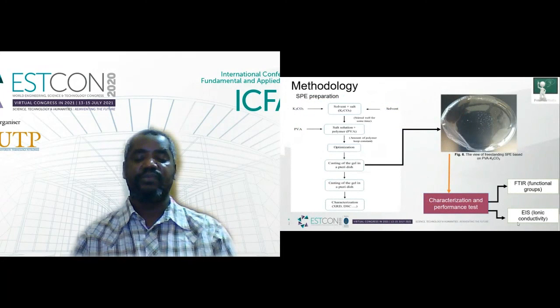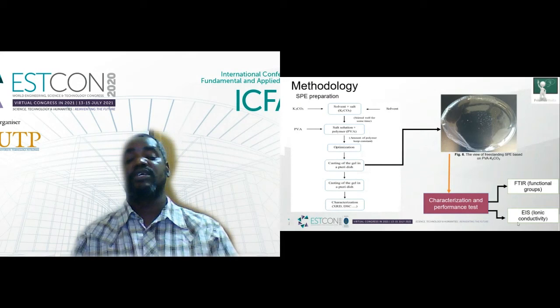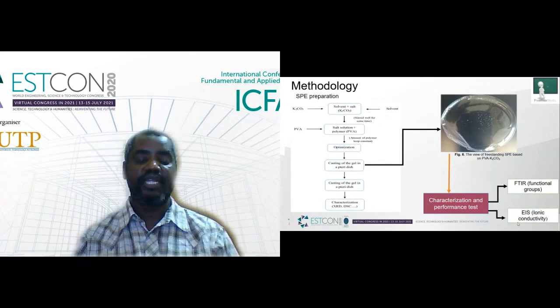We synthesize or develop our electrolyte from potassium carbonate as a source of ions and the polymer, PVA, as a polymer host or polymer matrix. We mix the two constituents together and then stir for some period of time until the two components, the salt and the polymer, have been completely dissolved, producing a very homogeneous and clear solution.